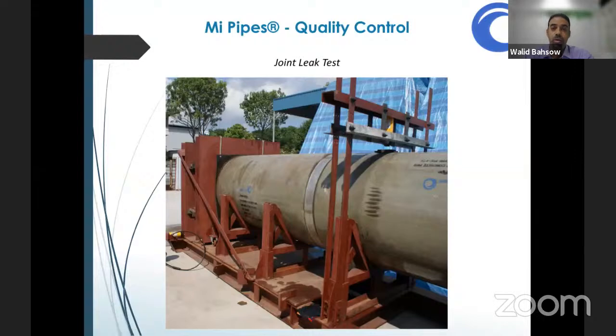Now, the standard requirement is 1 bar, but thanks to our joint design, we have tested our pipes and they can go to a much higher pressure. We've reached internal pressures of around 5, 6 bars, and for some sizes even 10 bars. If we're talking about deflection, including the deflection, 5 bars. And for the external pressure, we have reached pressures of about 4 to 5 bars.